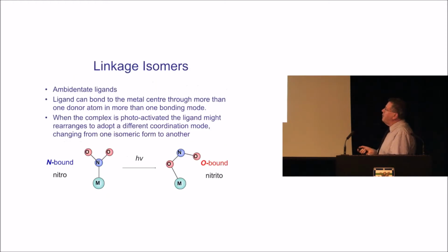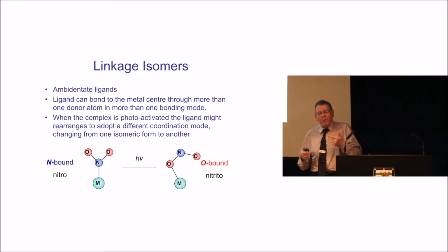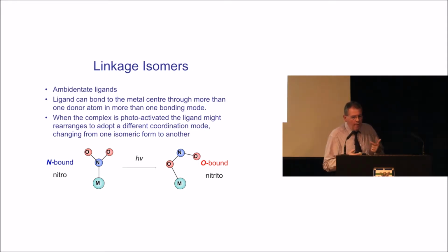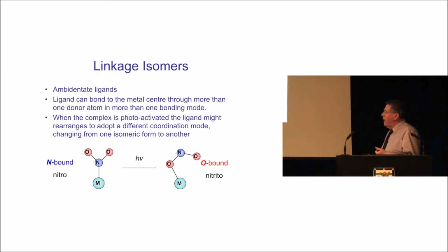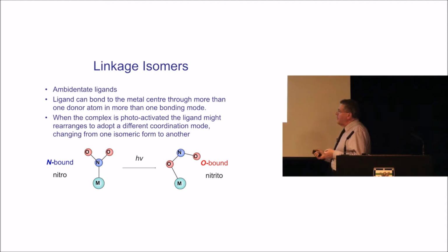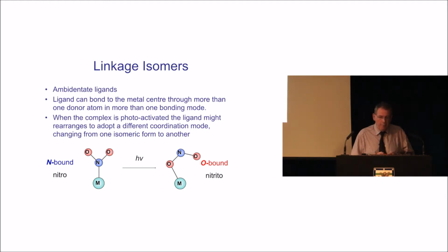And we thought linkage isomers would be a good place to start because you actually get real atom movement here. So a whole set of ambidentate ligands, those are ligands that can be bonded to the metal in more than one way. And you can see an example here. There's a nitro group bonded through nitrogen. In solution, it's been known since the time of Werner that if you irradiate with light, you can convert to the O-bound nitrito form. Can you do this in the single crystal?